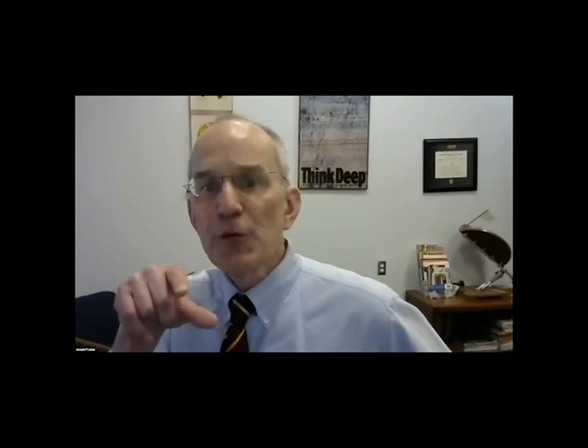Okay, so for your first part, we haven't looked at that. So that's an interesting point. The only thing I would say, as it relates to the second part, I showed it quickly at the end. We were successful with that pre-crack. And of course, that started from the notch. But now we have a pre-crack. That length was about 4 millimeters. The growth in the pre-crack, in terms of the alpha value, was, if I recall correctly, around 26 degrees. Whereas now, when we fractured that specimen that had the pre-crack, the alpha value was about 30, the average. So we still need to look closer at this data. I'm giving you the excuse that it's very new, so it's not published yet. But we didn't see a change in the mechanism, so it's largely the same.